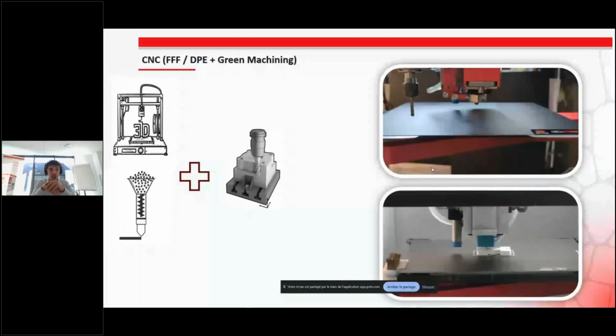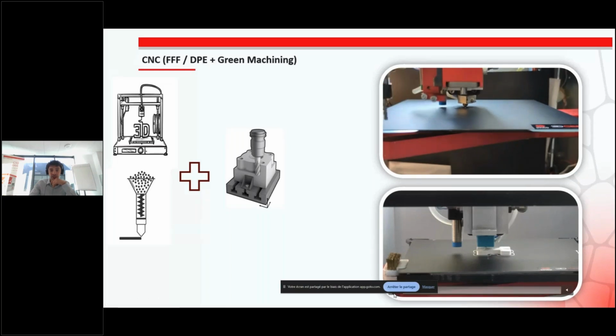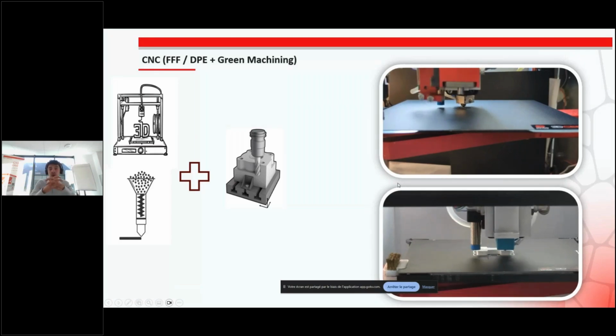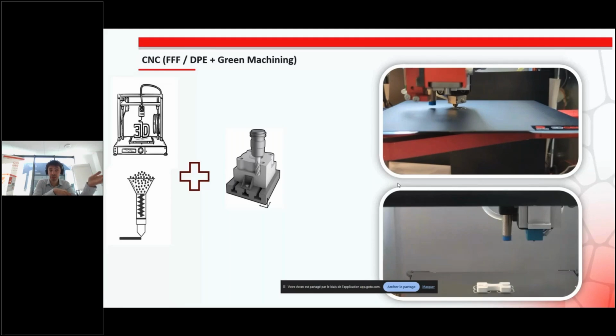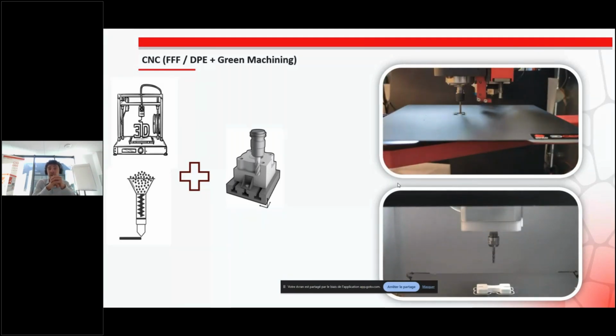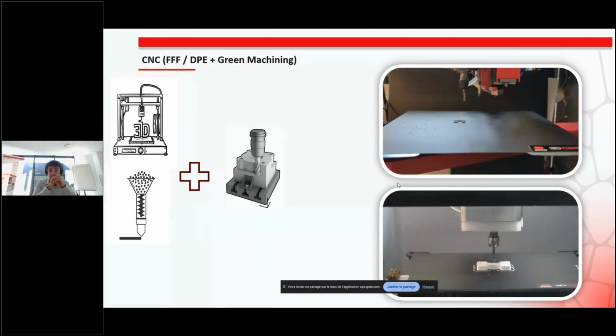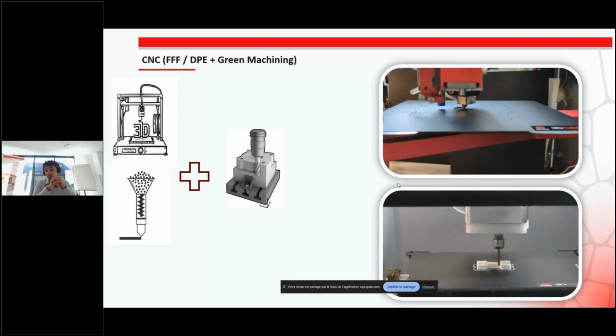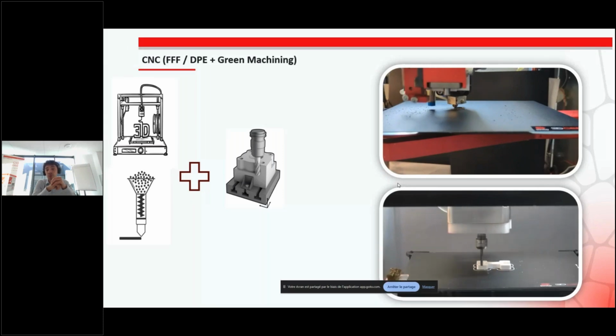And as I told you a few minutes ago, one of the strengths of this machine is the possibility to combine printing and green machining on the same printer. So if you want to improve the surface aspect of the part, for instance, it's possible to print and to machine at the same time. So you can have two heads on the printer. One head for the printing, which could be FFF or pellet extrusion, and another head for the machining of the part. It's very useful if you want to improve the surface aspect or to improve the accuracy of the part, for instance.